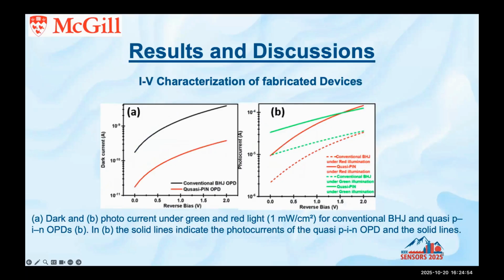To speak more, these are some of the results that I'm presenting here. The dark current of the photodiodes at zero bias shows a 10 times improvement. And since we look at the dual wavelength sensitivity for both red and green, it shows a 3 times improvement in the photocurrent for the new devices, and 4.4 for the red wavelength of the new devices.